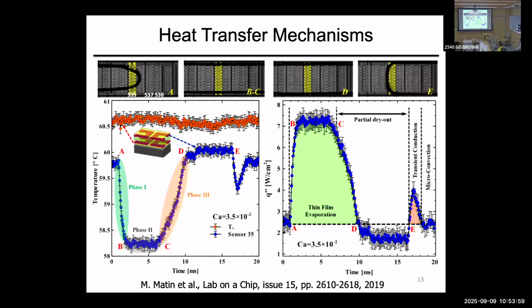And then essentially the microlayer evaporates, the liquid evaporates, and then the surface temperature recovers. And then as the bubble moves all the way, at the end this is rather dry now, not fully dry, but basically dry because these corners are still dissipating heat. And then the trailing edge of the bubble moves over the surface and quenches the surface, and then you get another event. So if you look at it, you have thin film evaporation, dry out, a transient event, and microconvection. It's amazing how you start from here and end up here in a process that people think is chaotic.